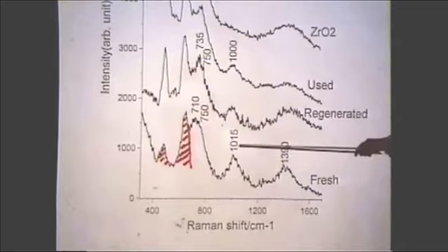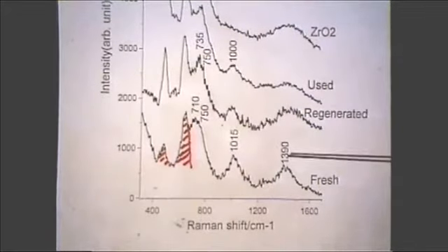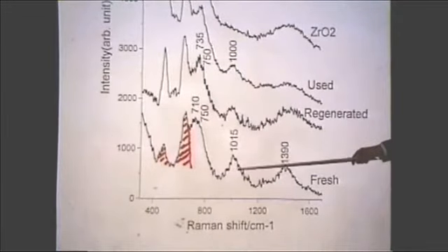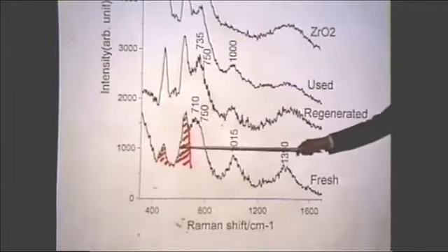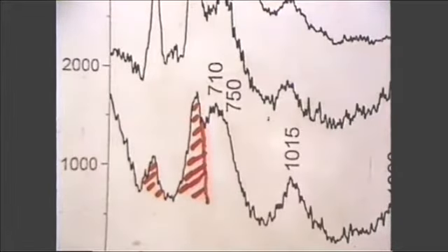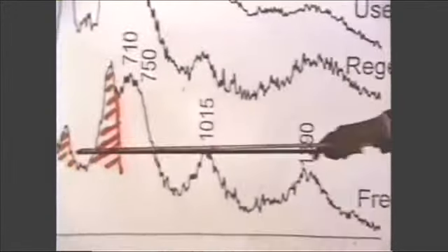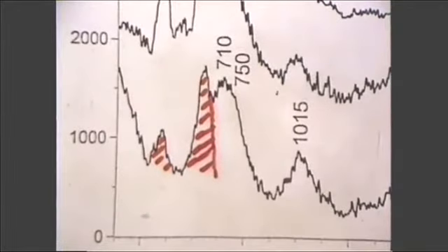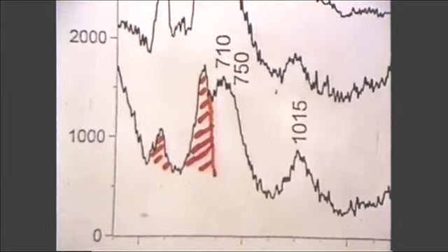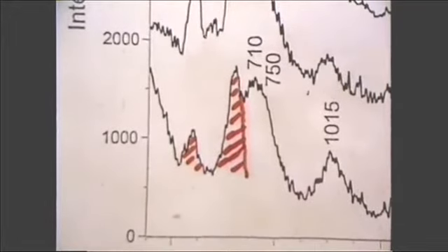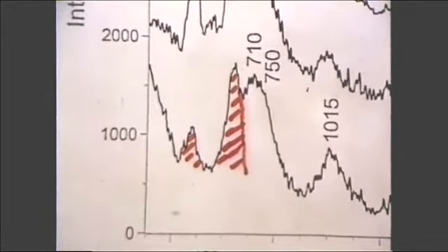These bands here are characteristic of the sulfate groups. This region here is characteristic of a sulfur-oxygen double bond, and this band here is characteristic of a bridging oxygen between sulfurs. These peaks here are what we would expect for the position and intensity ratio of peaks from the tetragonal form of zirconia. And it's known, actually, that you need the tetragonal form of zirconia to have an active catalyst, the sulfated tetragonal form of zirconia. There's some other interesting bands here that we don't know what they mean at this point, but they're in the zirconia region. All right, so that's the fresh catalyst.